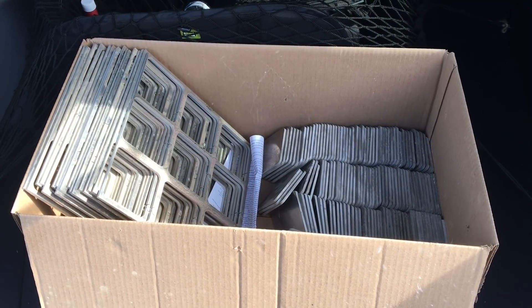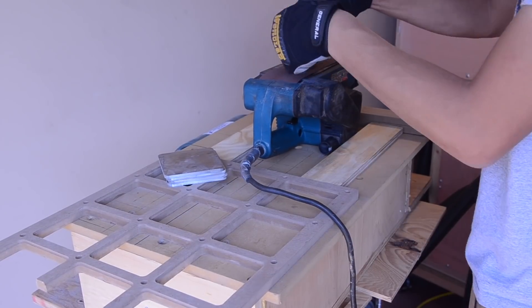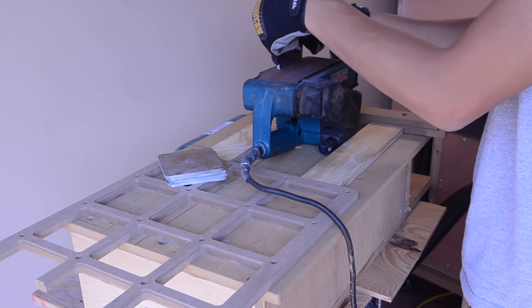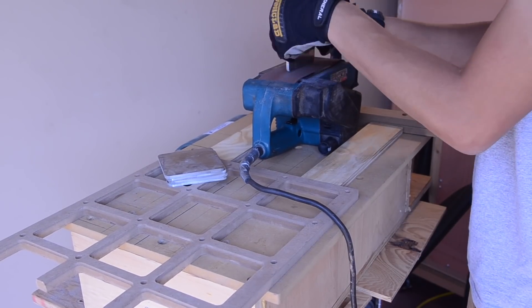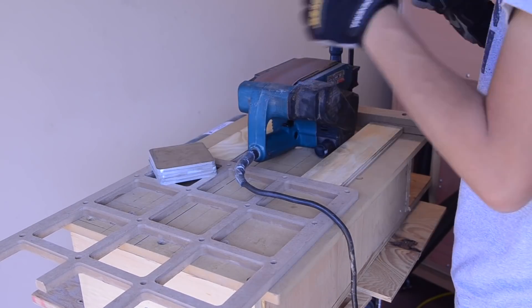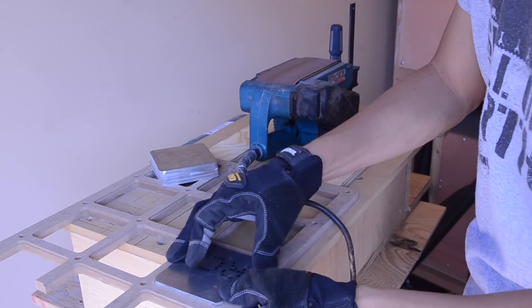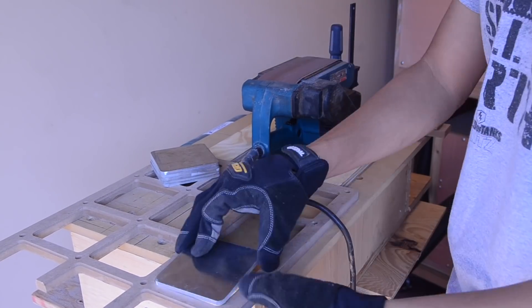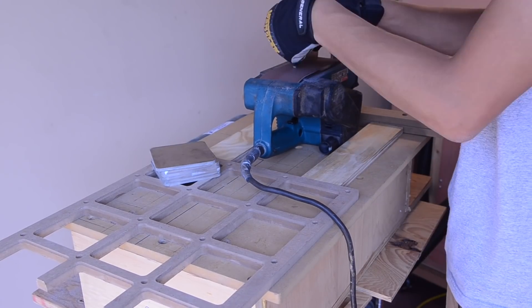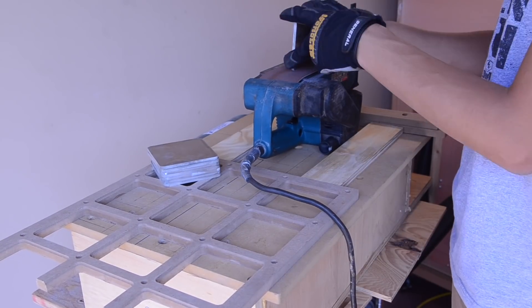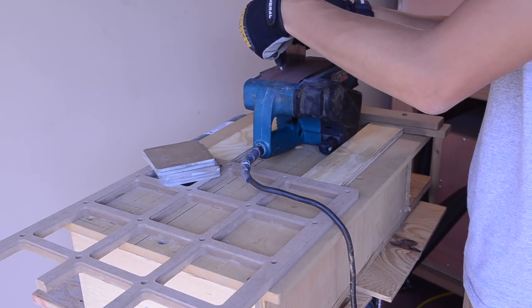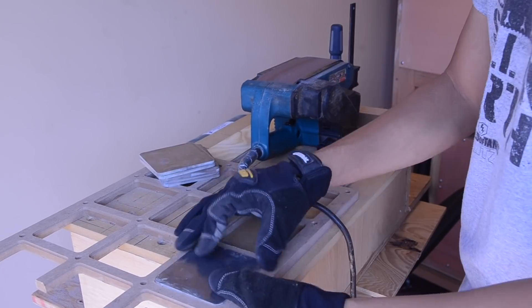Honestly, if I hadn't already purchased square foot plates, I would have preferred to send 2x4 foot sheets of aluminum or larger for waterjet cutting. It would have been more efficient and resulted in less waste, but the stability advantage of a larger plate never crossed my mind until it was too late. The only thing I could do to mitigate this issue was to remove as little material as possible from the blanks until after machining. By sanding the edges flat, I was removing a couple thousandths of material and worsening the fitment problem. What I ended up doing was using part of my fixturing plate as a go-no-go check. I'd sand off just enough of the entry point spur and sometimes an adjacent side for the blank to seat firmly in the fixture. That's as far as I would go with sanding until after machining.